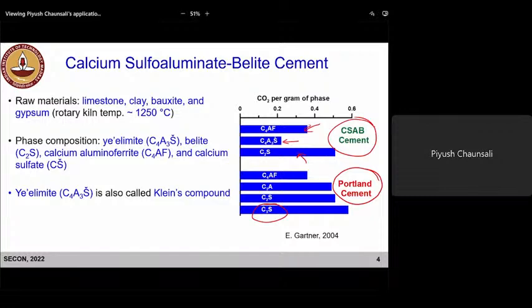And to make CSAB cement, we don't have to go to really high temperatures. For example, for Portland cement, we have to go to 1450 degrees Celsius, but the CSAB cement can be manufactured at 1250 degrees Celsius. So there is a reduction in the temperature requirement to manufacture this cement. And the raw materials are similar to what we use for Portland cement: limestone, clay, bauxite, and gypsum.